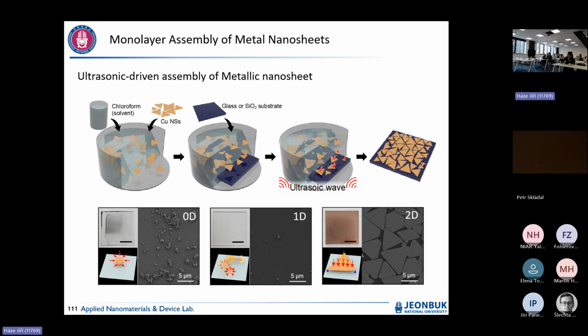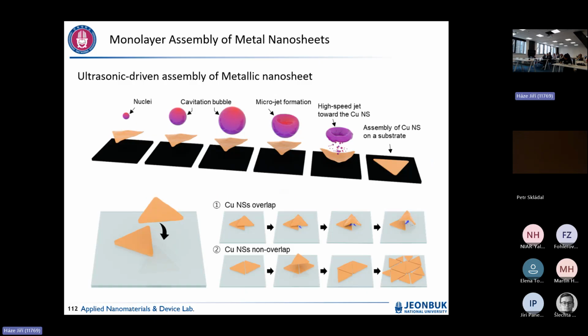We tested nanoparticles and nanowires, and only nanosheets allow assembly. It was really hard to find a reference paper. There was no reference paper. It doesn't make sense, right? So we tested a lot. Why? You can see here, the cavitation bubble grows and increases, then collapses, and the bubble pushes the sheet down on the surface.